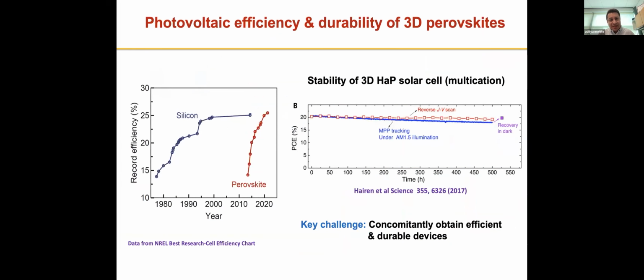All right, so the story really starts here for photovoltaics. I hope this is not a repeat of what the previous speaker may have shown, but nevertheless, we are here because halide perovskites have shown incredibly efficient photovoltaic devices, with efficiencies now surpassing that of single junction silicon solar cells. But very few times are curves like the one on the right shown, where if you take the stability of a typical 3D perovskite solar cell, you will see that this is a good device over 20%, but it tends to undergo degradation over about 500 hours. And this is really not acceptable if you're trying to put a photovoltaic technology on your roof for about 20 years, or even 10 years for that matter.